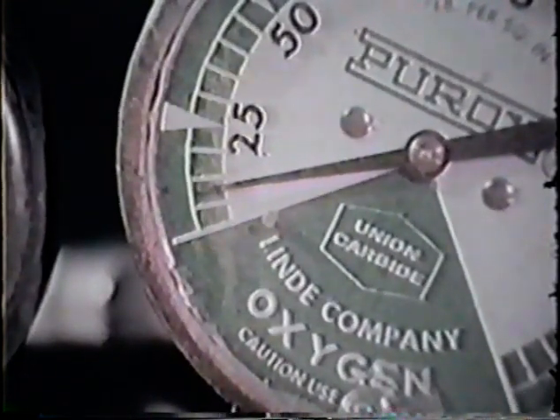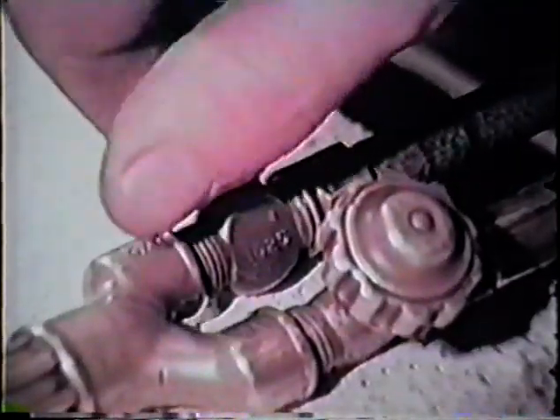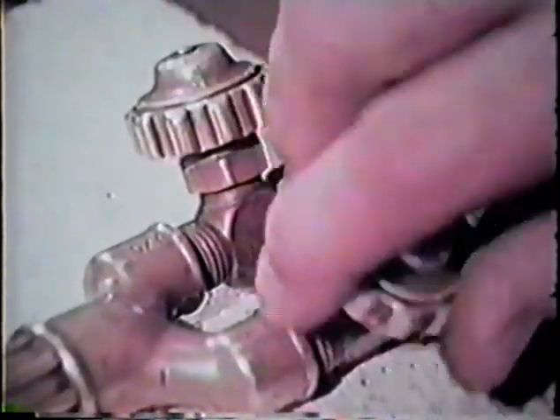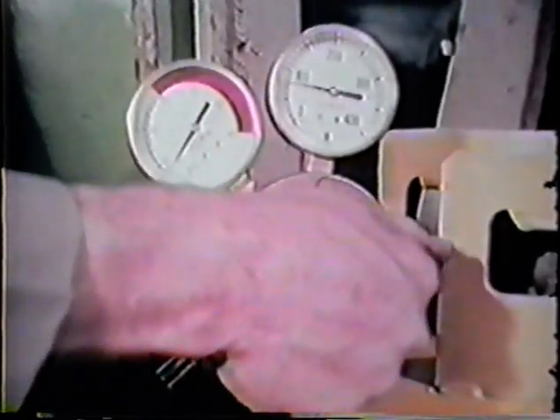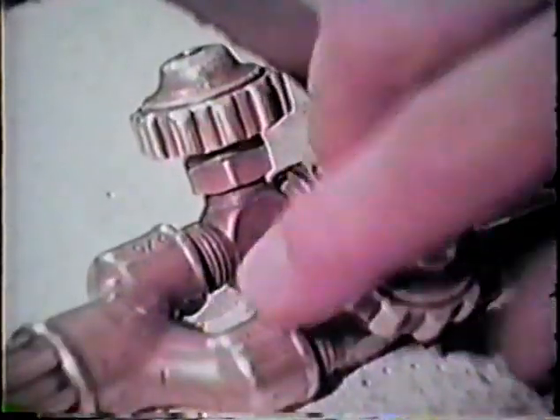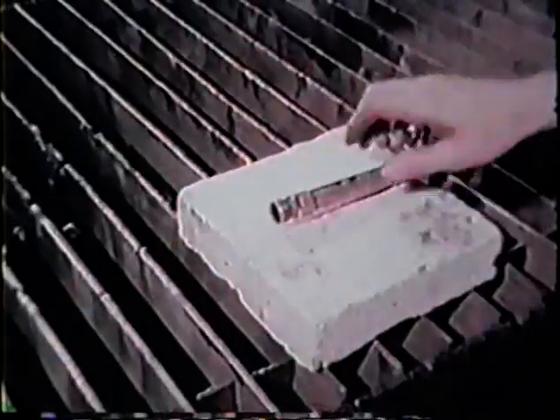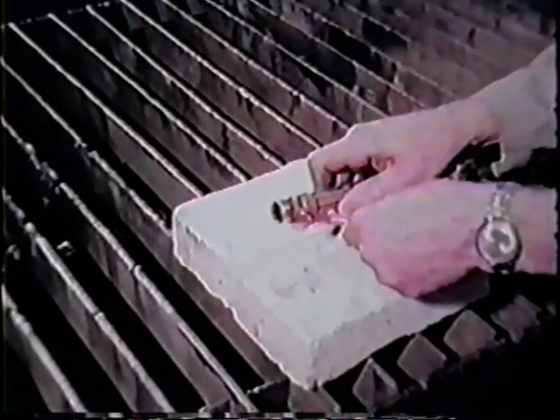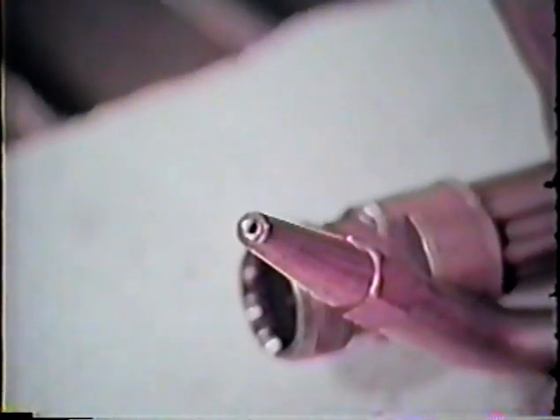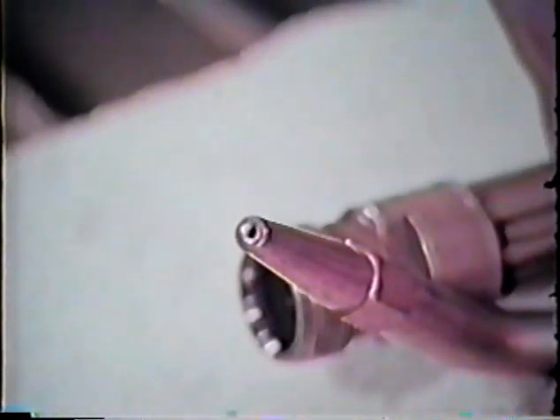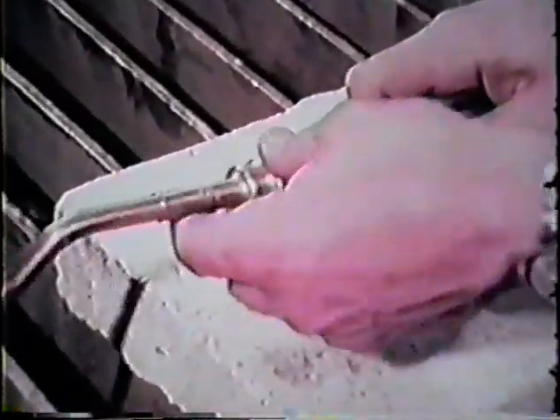Continue to purge the oxygen for 5 to 15 seconds. Then turn off the torch valve. Next, adjust the fuel line pressure to 1 to 5 pounds and purge the hose up to 15 seconds. Purging the hoses eliminates any mixtures of gases left in the hoses, so no flashback will occur when the torch is lit. Before lighting the torch, attach the proper welding tip for the job. The MAP gas tip has one large hole in the center countersunk to stabilize the flame. Screw the tip to the torch and tighten it down hand tight.